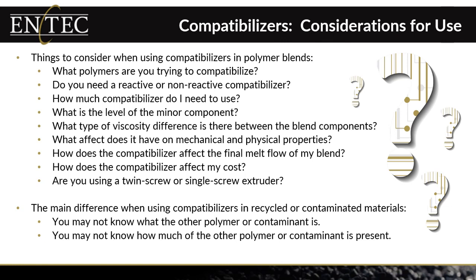I have a comment here on if you're using a twin screw extruder or a single screw, it's not quite as important when you're talking about adding it as a compatibilizer or coupling agent. But if you are also looking for some impact modification and you want to use higher loading levels, then twin screw extruders are preferred, or single screw extruders with a mixing zone. But once again, it depends if we're going to use a chemically coupled or a non-chemically coupled compatibilizer.